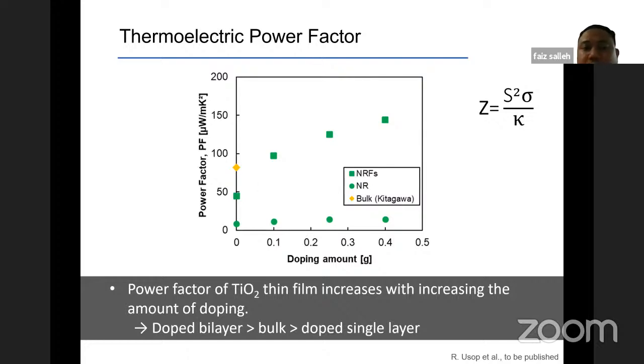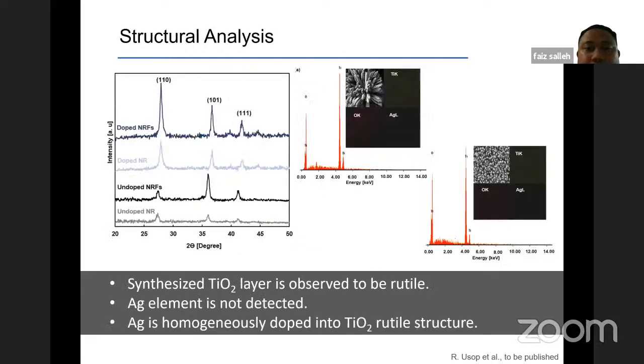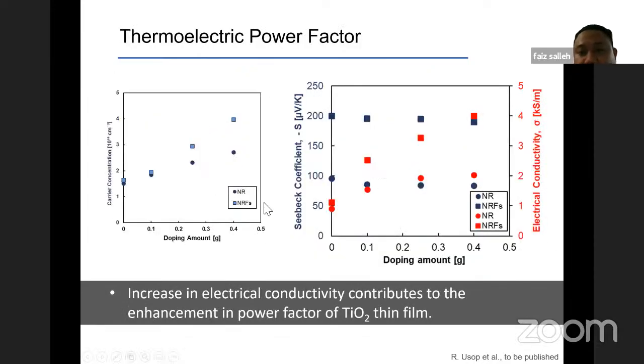So what we consider is that through doping, we can increase the carrier concentration. We have also measured the carrier concentration by using the Hall effect measurement. We can see that by increasing the amount of doping, the carrier concentration inside that bilayer and single layer structure is also increased. When we introduce silver or argentum inside the TiO2 lattice structure, we expect that it will increase the oxygen vacancy on the surface, that will introduce more carriers inside the TiO2 layer.